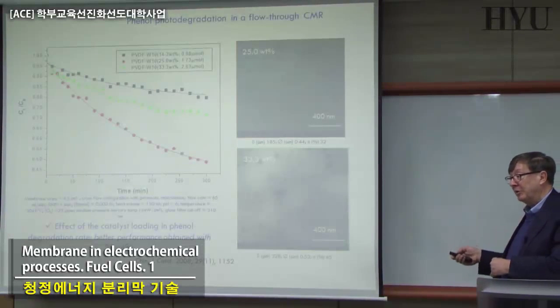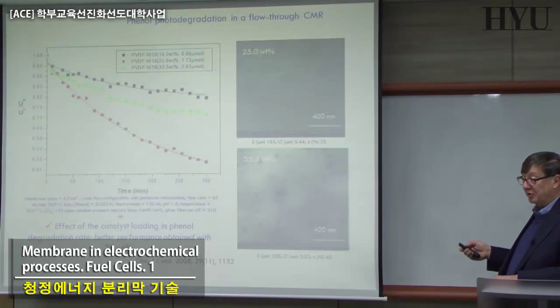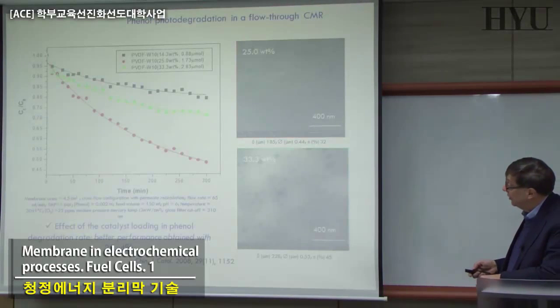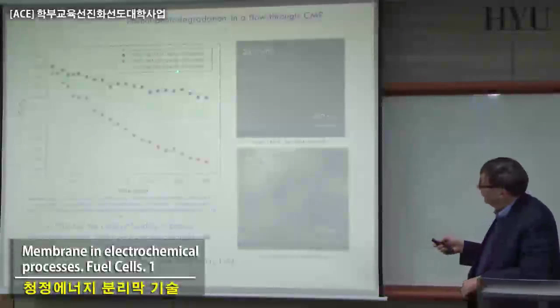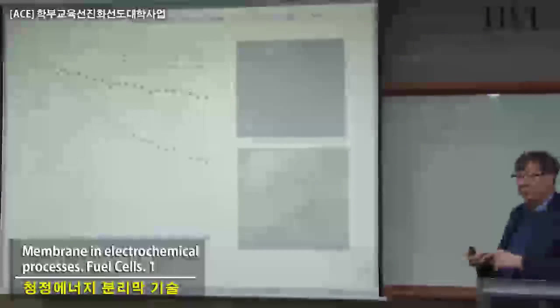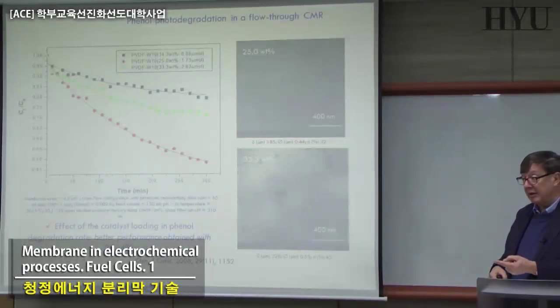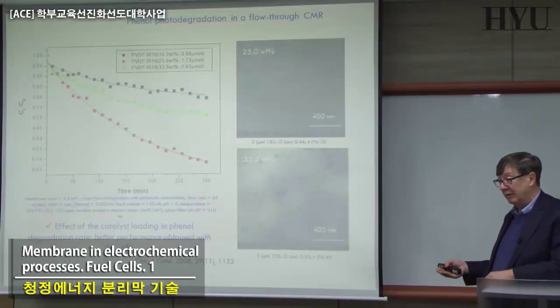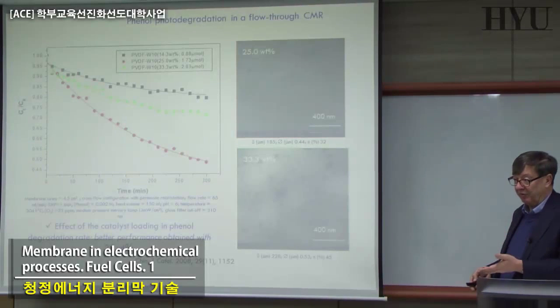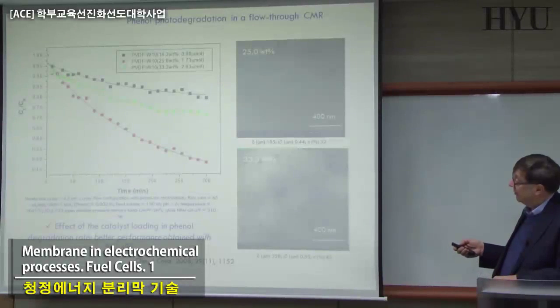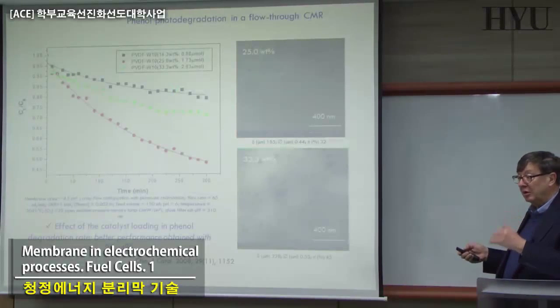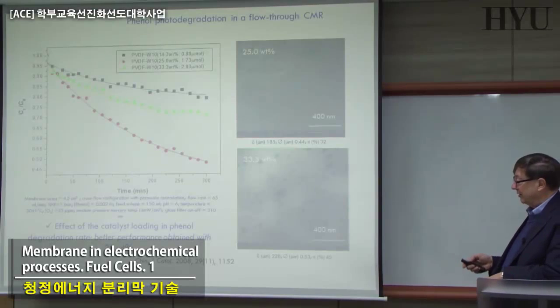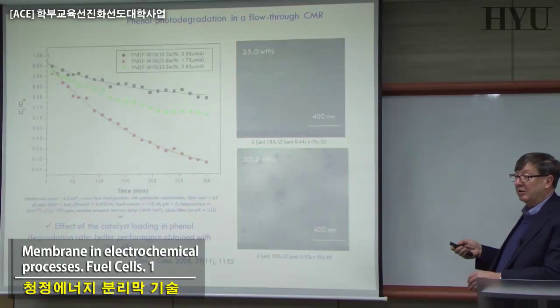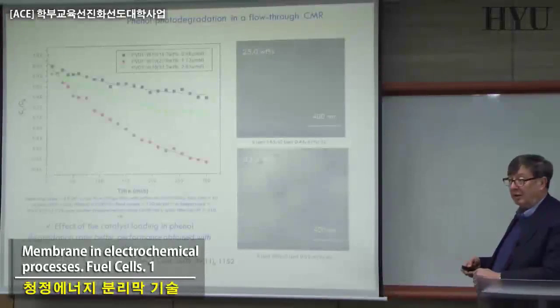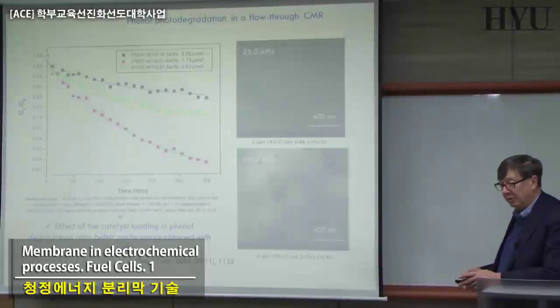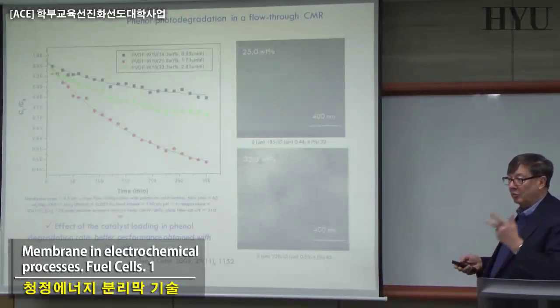And now when you have been making the membranes, charged with a certain level of catalyst, I don't see here the data. Oh yeah, there are some data up here. You have to be sure, by the way, of the amount of catalyst you can immobilize, which is directly related to the behavior as a catalytic system. More catalyst, more efficiency, and this behavior, however, you cannot keep increasing. If you study the system, you will see that when you increase more than 20, 25%, 30%, you can start to expect two problems.